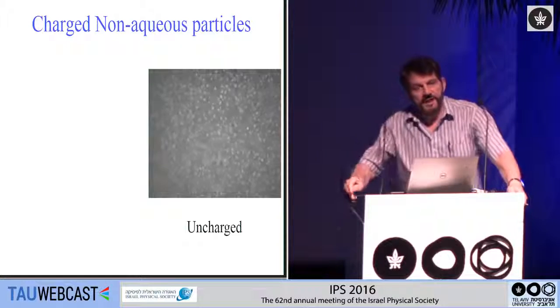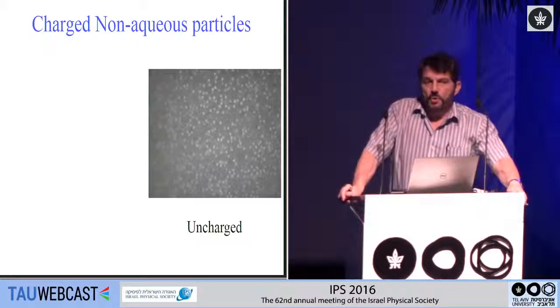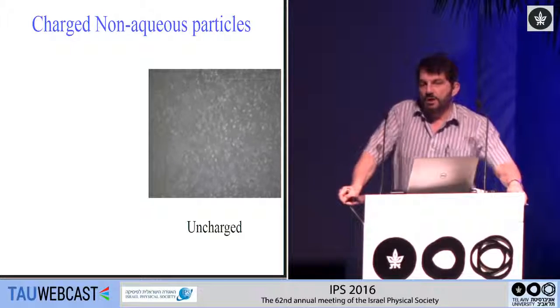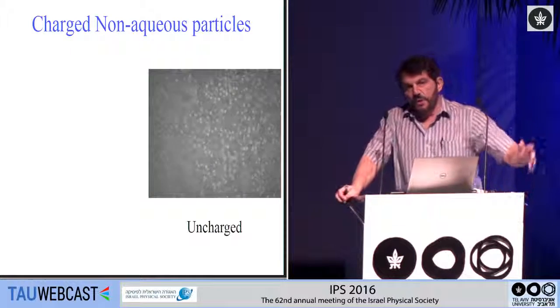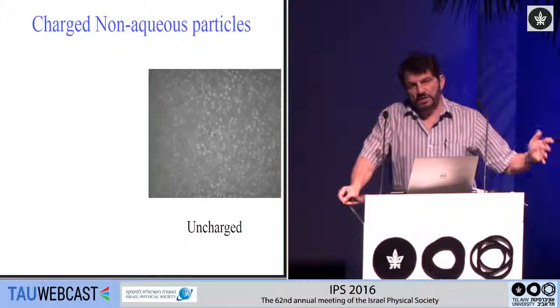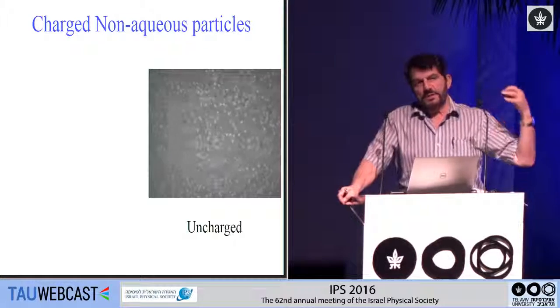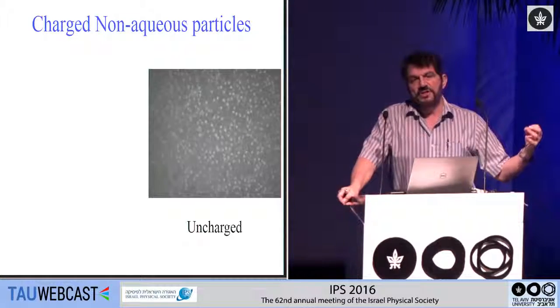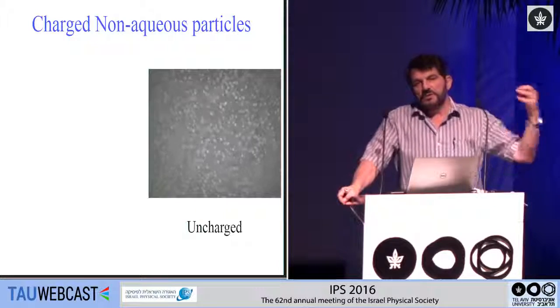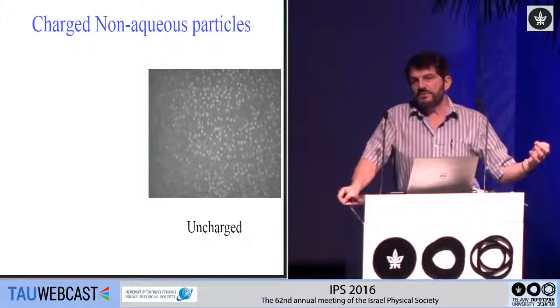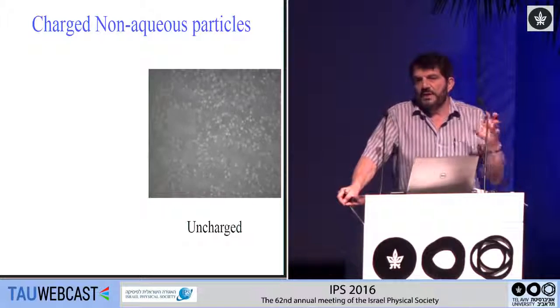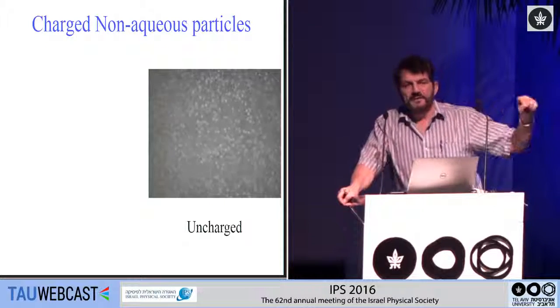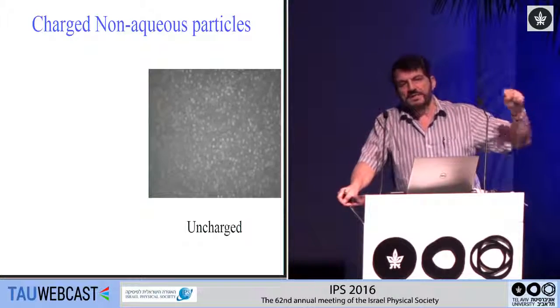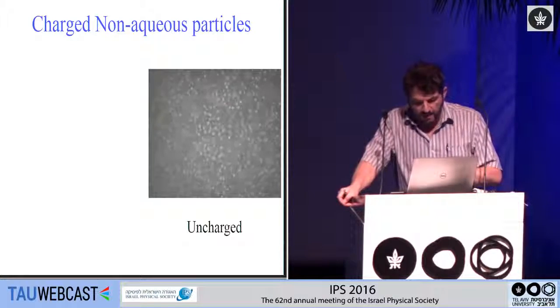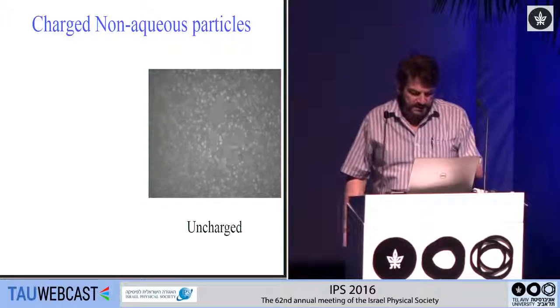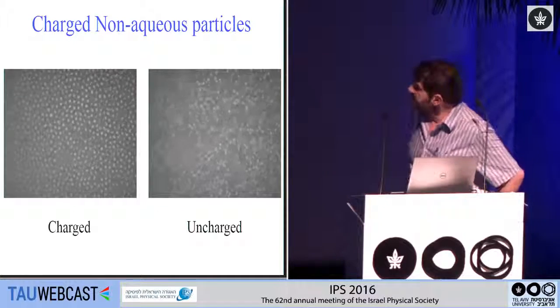However, even though this is an oil, we've developed methods to charge the particles. And normally you don't think of putting charge in an oil. However, if you can somehow carry the charge in the oil away from the particles, you can allow them to be charged. The way you do this is to put surfactants in the oil that create very, very small regions of high dielectric constant in which the charge can be located and which solubilizes the charge. And if you do that, you get a system that looks like this.